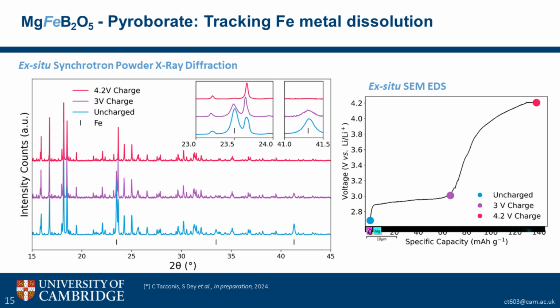And what we're able to see here is that there isn't a significant change in the main cathode structure. We didn't consider this as conclusive proof of the fact that we weren't demagnesiating the structure, because one of the strengths of polyanion systems upon demagnesiation or delithiation is that they don't change in volume that much. So in principle, a lack of change of structure for these materials doesn't actually mean that you are not demagnesiating that much.